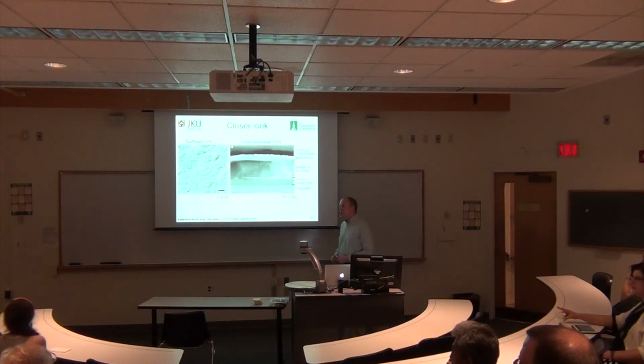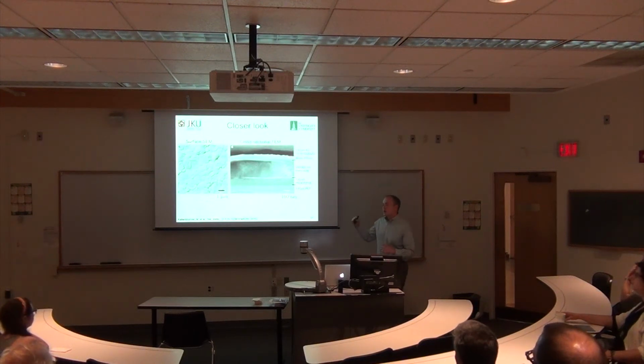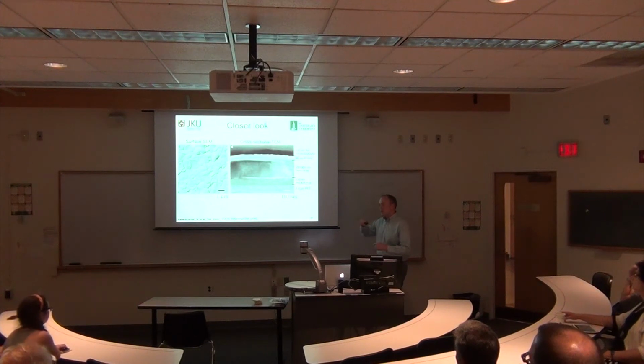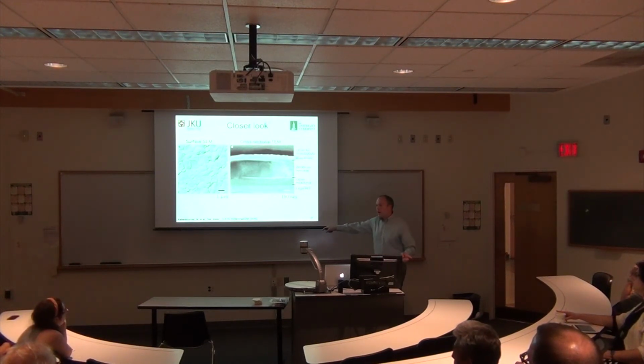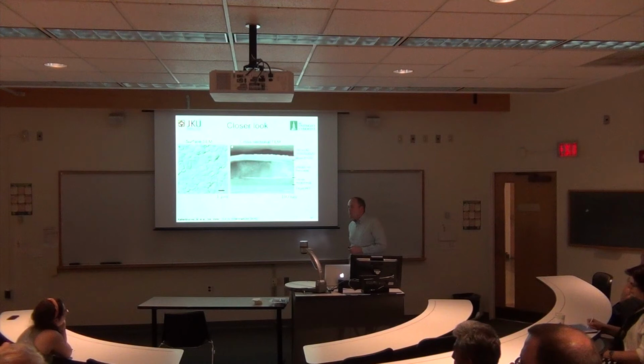Is there some kind of a junction? Is there a PN junction? So what we have is just a semiconductor with two selective contacts. And so you have a gradient buildup because electrons can easily leave one way and holes can easily leave the other way. And so you get a concentration gradient that drives the current. So is it like Schottky? It's essentially like two Schottky junctions, one on either side, an N selective and a P selective on either side.